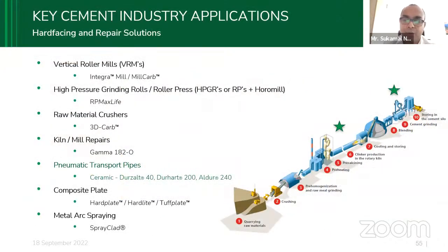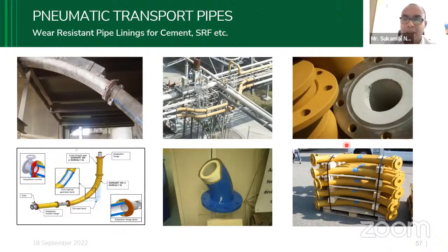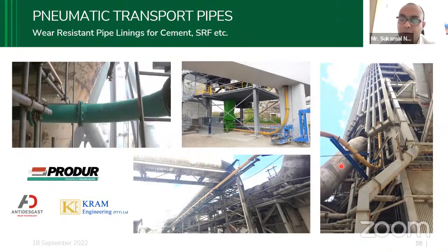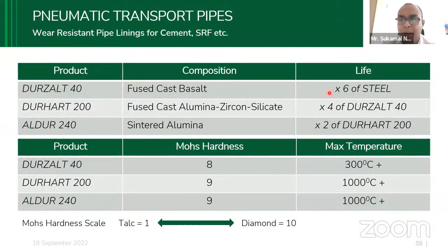Next come pneumatic transport pipes. There are several transport pipes in the cement industry, where because of the cement they get quite a lot of erosion and corrosion, and we do a lot of repairs of these components. Depending on the life the customer wants, we recommend several types of products which could enhance the life by 6 times, 4 times, even 2 times. And the maximum operating temperature also plays an important role.